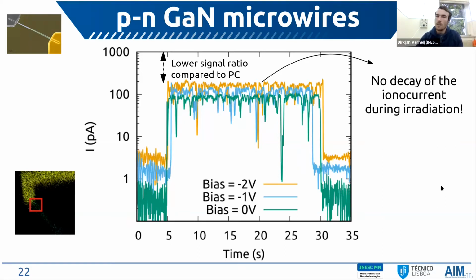We do observe a slightly lower signal ratio when comparing the data to the photocurrent data, but this doesn't have to mean much, because one thing I haven't said, which is important to understand, is that when we irradiate a sample with UV light, the photons are all absorbed at the surface, or at least close to the surface. They do not penetrate inside the semiconductor. With protons, the story is different, because protons with an energy of 2 megaelectron-volts have a range of 53 micrometers in gallium nitride.